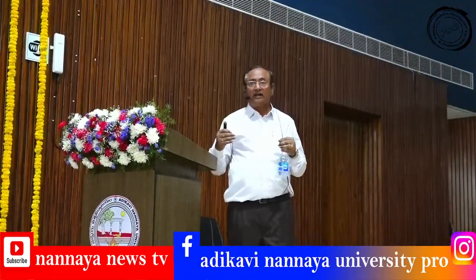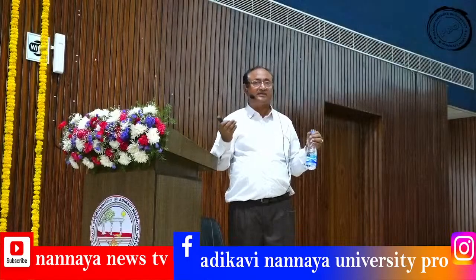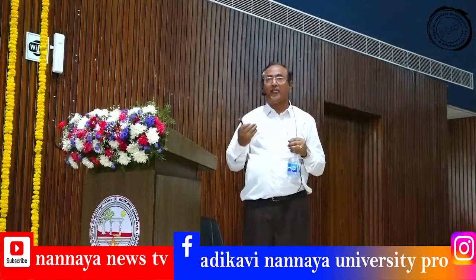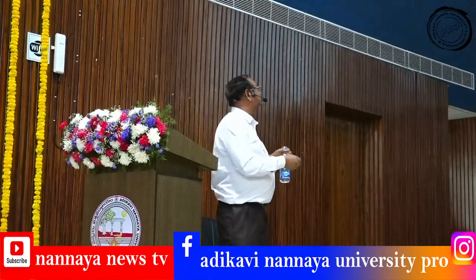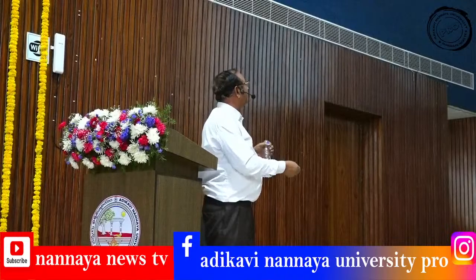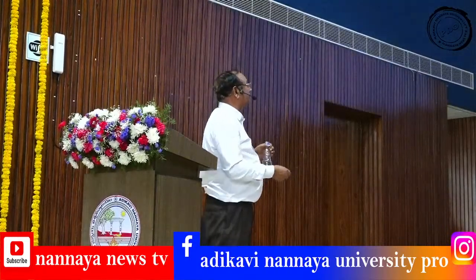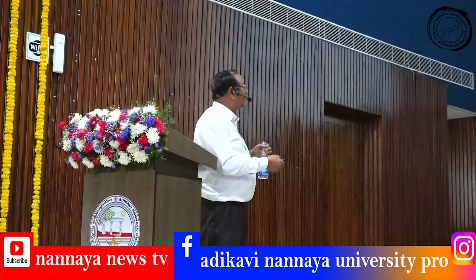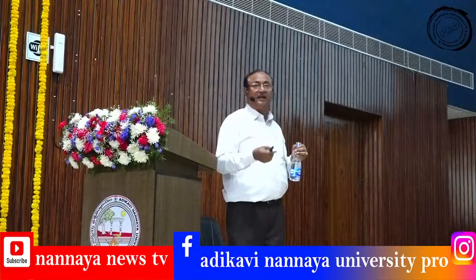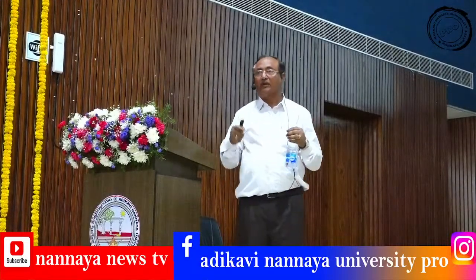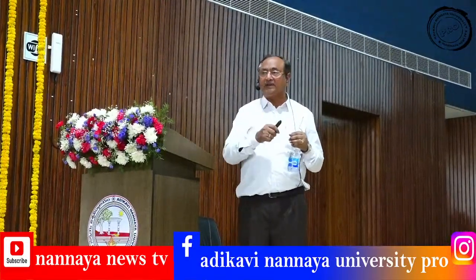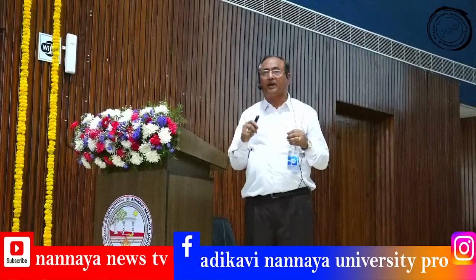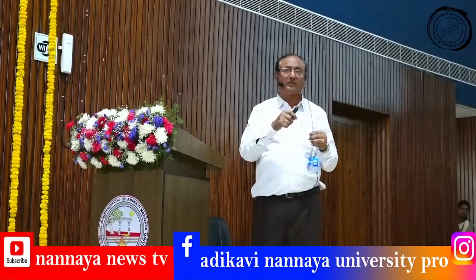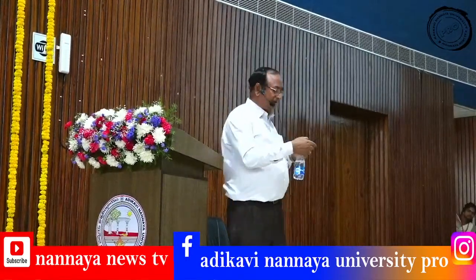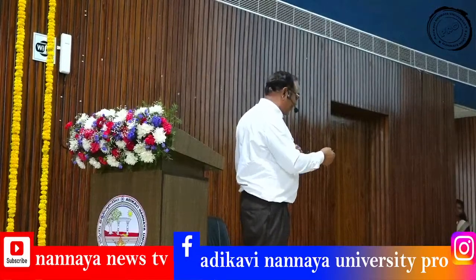So this is fed to the computer by this FT Raman, this Fourier transformation. With Fourier transformation, you can get the Raman spectrum. We have to do it 2 times, one with the sample and one without the sample. If the latter is subtracted from the former, you will get a Raman spectrum.